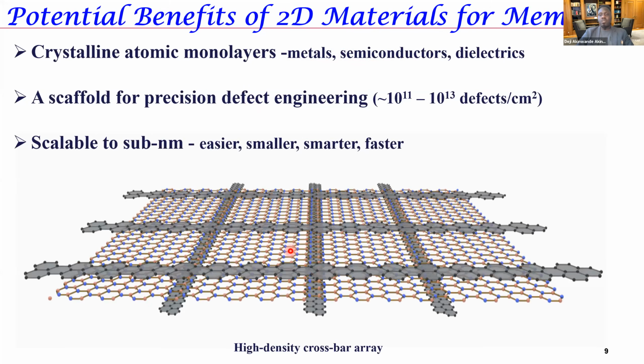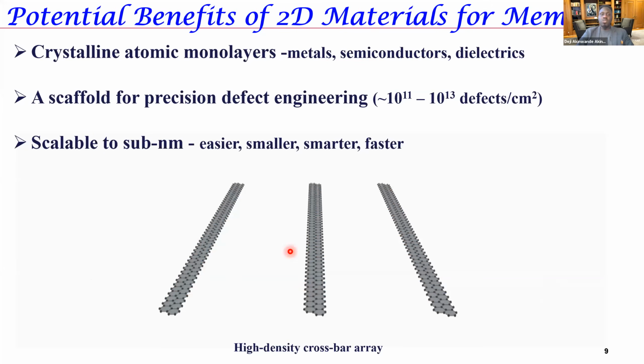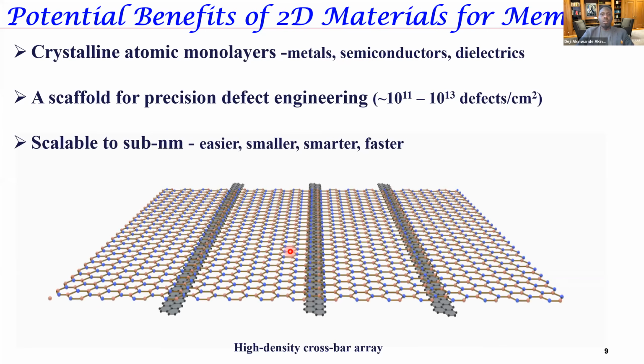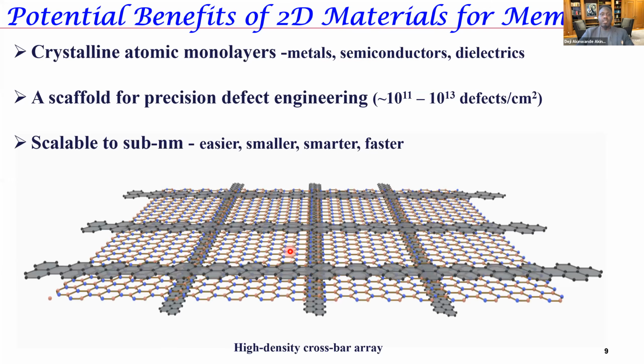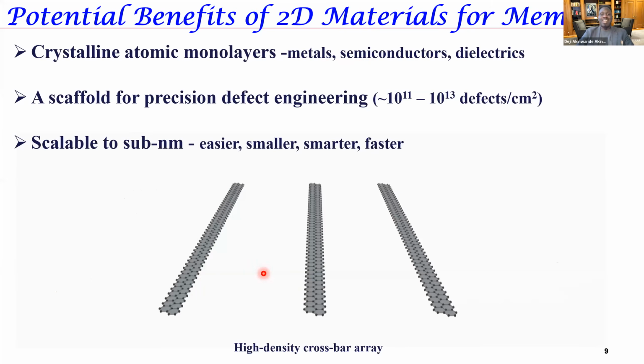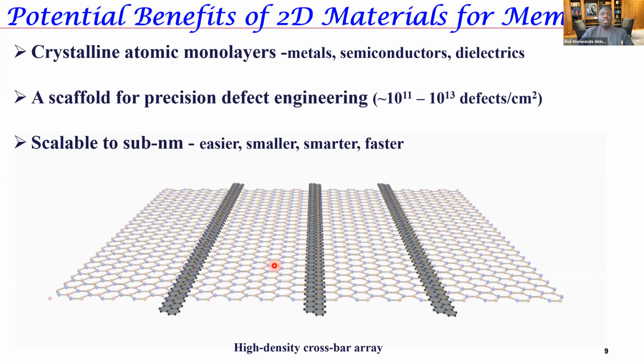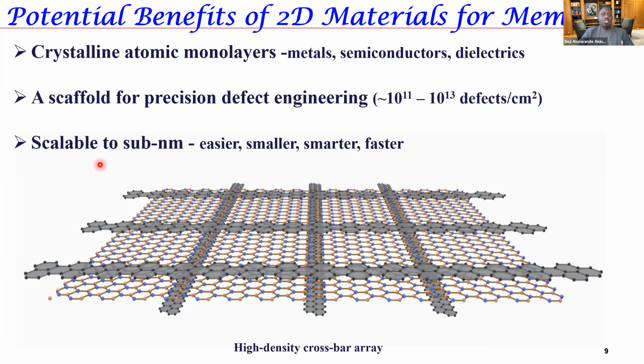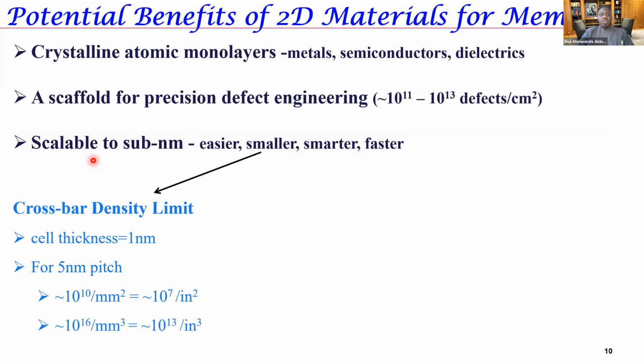You could control the defect density by orders of magnitude, unlike metal oxides where you get what you get. In these 2D materials, they're crystalline materials, so one can engineer the defects at pleasure. And it's very scalable, so it's easier.